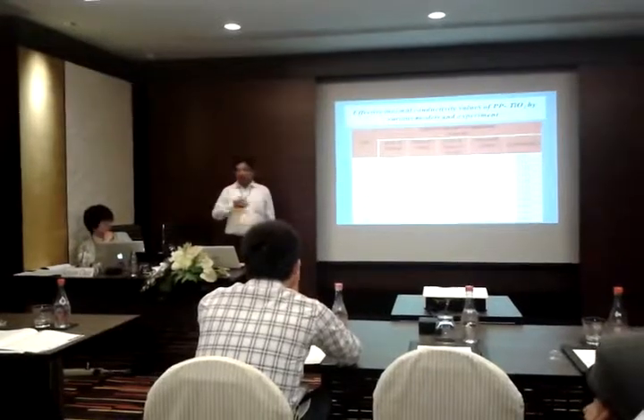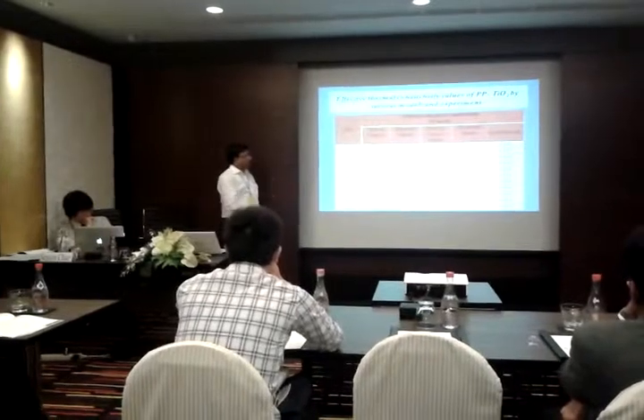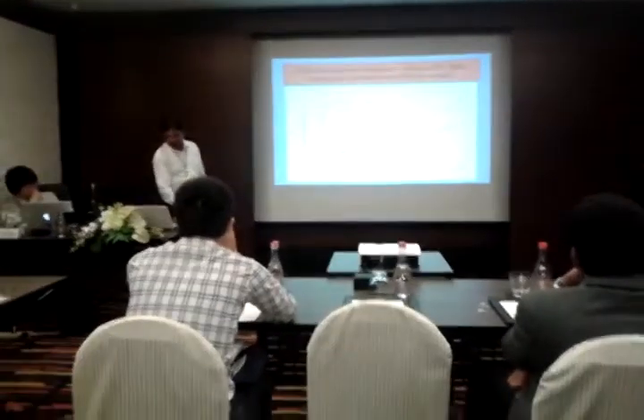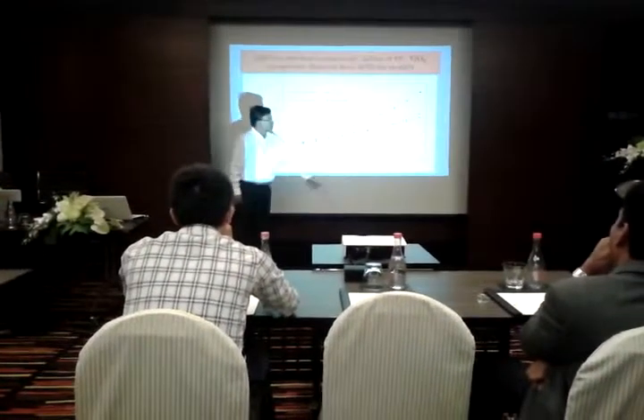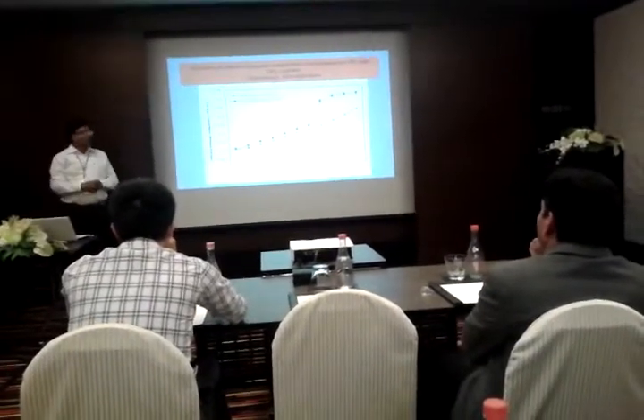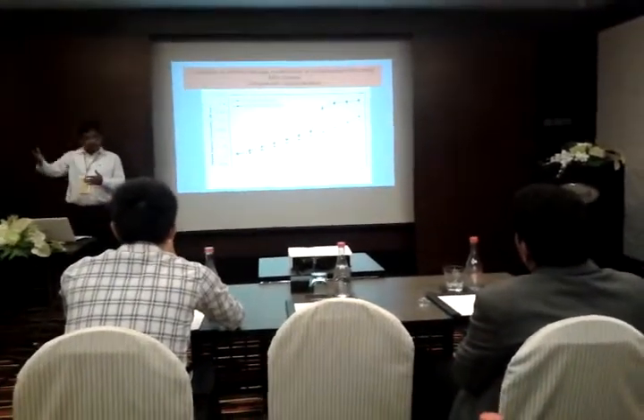We used other models proposed by previous researchers alongside our proposed model, and compared all these theoretical results with experiments using the Unitherm 2022 model. This table presents the comparison, and you can see that our proposed model is matching with the experimental results very closely up to a filler fraction of 15 percent. After 15 percent, there is a sudden jump in thermal conductivity, as often found in polymeric composites. That particular filler concentration is the percolation threshold — beyond that, there is a drastic increase in conductivity. So if you want more conductivity, go beyond the threshold; if you want less, remain within it.